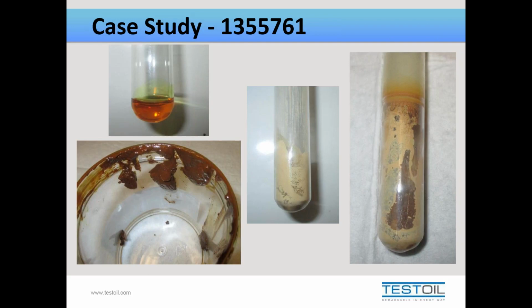So through the analysis, we first isolated out the different components, the lubricants, organic materials, and any inorganic materials. And we were able to find that during the analysis, there was glycol contamination, water contamination, oxidation products, and silicates. So the presence of the silicate really indicates to us that dirt was present in the system. Oxidation products indicates that the fluid itself had experienced degradation and was forming varnish. And then the water and glycol suggests that the system was contaminated with a coolant.